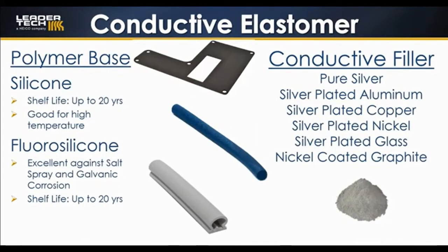LeaderTech's conductive elastomers are made from 2 polymer bases and are mixed with 6 different metallic fillers. Both the silicone and fluorosilicone polymer bases offer shelf lives up to 20 years. Fluorosilicone differs from silicone because it contains trifluoropropyl groups, making it highly versatile for outdoor sealing applications or environments where exposure to sunlight, ozone, chlorination, or aromatic hydrocarbons is common. With the polymer bases, we use 6 conductive fillers to make 11 MIL-DTL 83528 certified materials, and some compounds outside of the military spec.